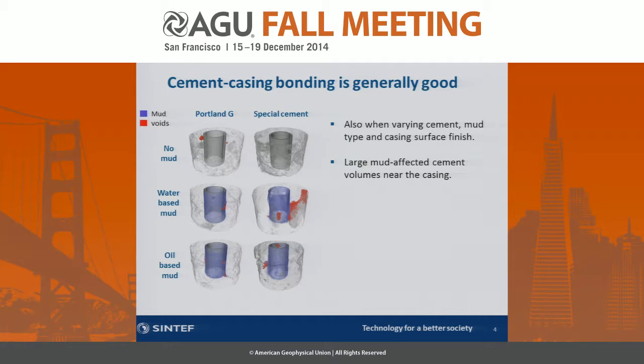So of course, to be able to determine any type of leakage from these samples, you would have to check the properties of this mud-affected cement in each case, because there was very little porosity that could be seen by CT. And what was interesting is that this very good bonding that we saw in this case seemed to be a geometry effect, because we were making these samples in autoclaves, and at the outer surface of the autoclave, you saw more debonding. So this is exactly the geometry that was used when we looked at the cement-rock bond. Then you had a rock surrounding a cement. So that might be something related to geometry there, and that's something we're looking into right now.